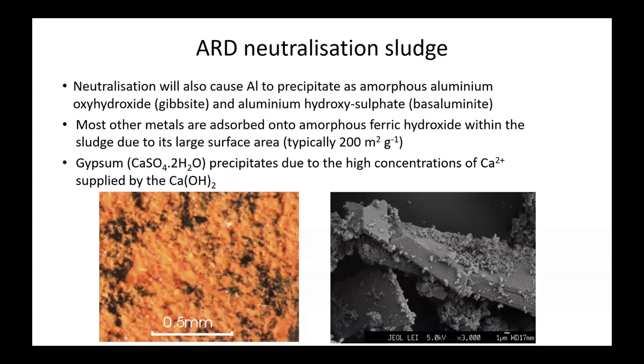And also, because you've added generally a calcium neutralizing agent, and there's a lot of sulfate in the water to begin with, gypsum, calcium sulfate, will precipitate. And so you end up with a sludge. It's typically orangey brown, like in the bottom left, and contains lots of gypsum crystals, like we can see in the SEM on the bottom right. Next slide.